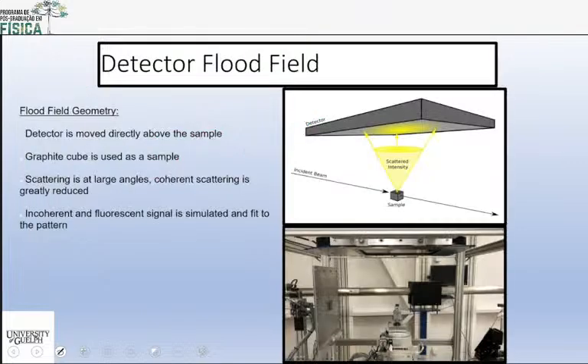So we did a lot of work, and there was a lot of calculation involved. We put a detector. So here, what you see is the beam hits a sample here at the bottom. You see that? And then what we did was we put the detector on top, like a roof. Okay, and X-rays hit the detector, and our sample is this big block of carbon, and we have Compton scattering. Remember Compton?